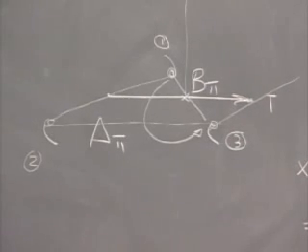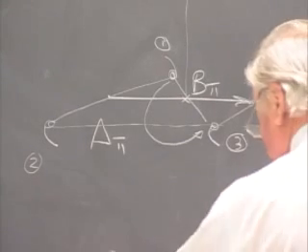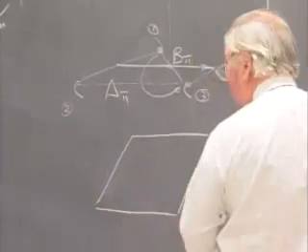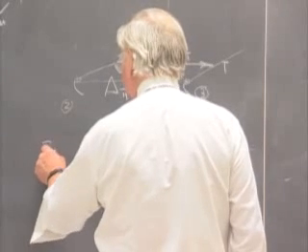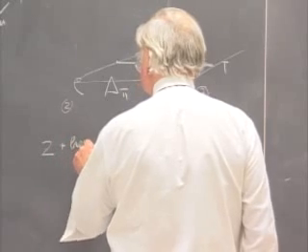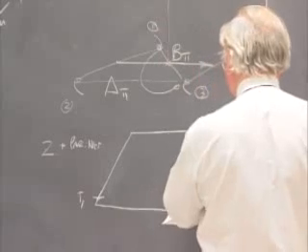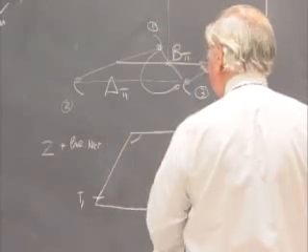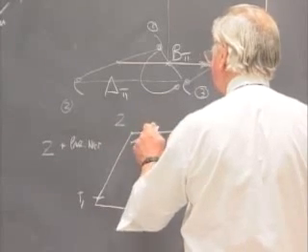And now lickety-split I will derive again, and I don't have to apologize for going fast because I did do it last time. Let's ask what happens when we combine a twofold axis with a parallelogram net. In this two-dimensional lattice, there are two translations, T1 and T2, of arbitrary magnitude with some angle between them that's arbitrary. And to this lattice point, I'll add a twofold axis.